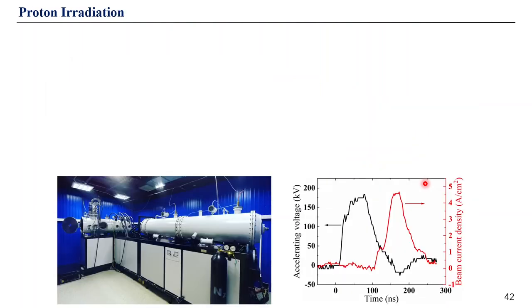So for that we place our devices in the vacuum chamber of a proton pulse accelerator. So here we see the accelerating voltage pulse and the corresponding proton beam current density. By integrating this proton beam current density pulse, we get the accumulated fluence, which is 2 10 to 12 protons per square centimeter, which corresponds to about 6 years of operation in low Earth orbit.